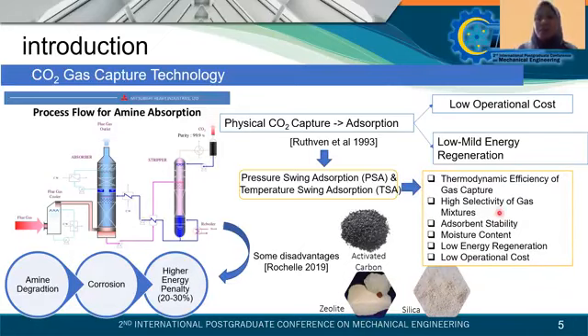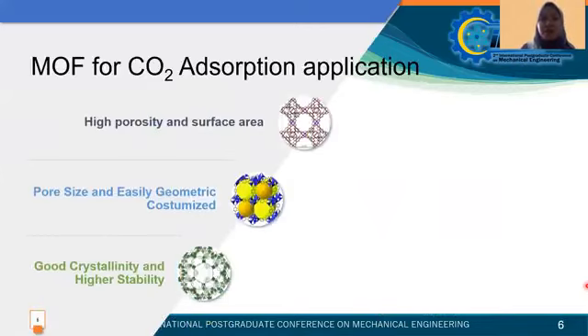Here are the characteristics. And some adsorbents that have been widely used in the industry are activated carbon, zeolite, silica gel, aluminum oxide, metal oxide, and also the metal organic frameworks. In the past 2 decades, the new adsorbent called metal organic frameworks, or MOF, is believed to be a viable solution for the application of CO2 adsorption because it has many advantages. They have high porosity and surface area, the pore size is very easily customized, and also it has good crystallinity and higher chemical stability.